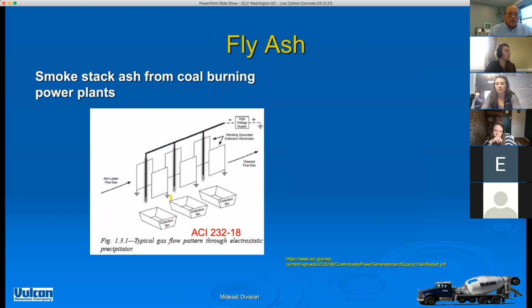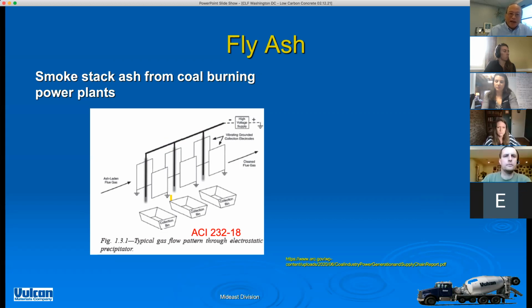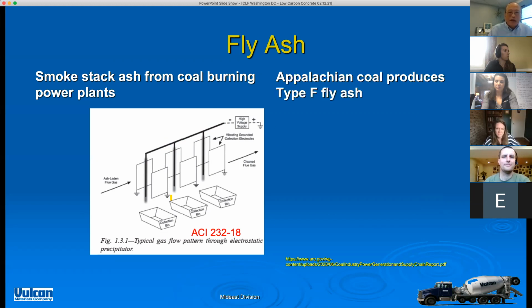Okay, well, fly ash. What is fly ash actually? In coal burning power plants, you burn coal, you're going to get ash. That ash is going to fly up the stack. That's why it's called fly ash. And by EPA regulations, emission standards, the power plants have to capture that ash, by various means, using electrostatic precipitators, and then drop it into various containers. So that's how you get fly ash. There is a companion to fly ash. It's called bottom ash, because that's the ash that drops to the bottom of the smokestack. So, very creative names there. Anyway, advance another one, please.